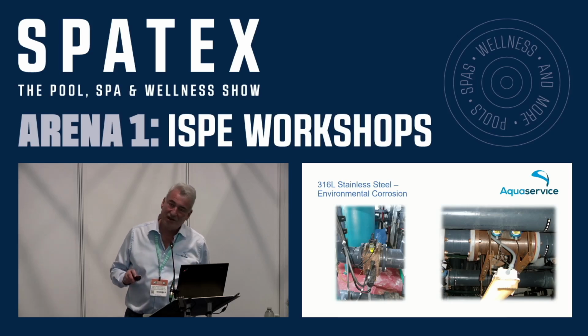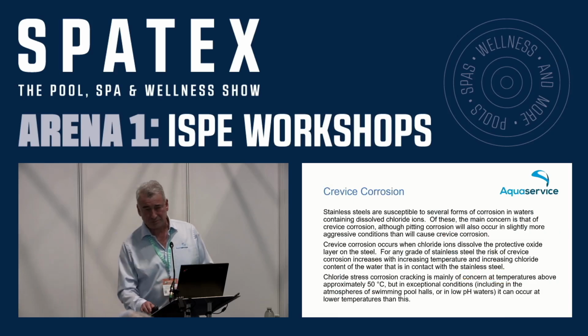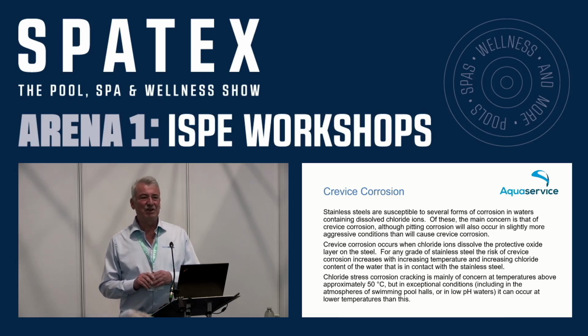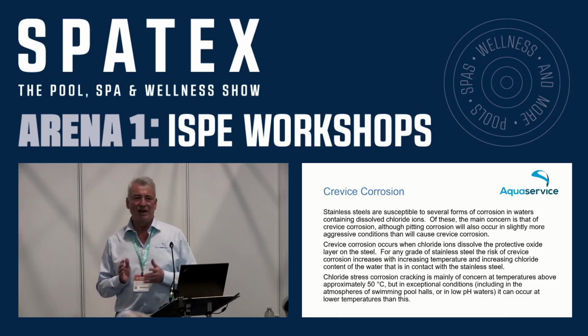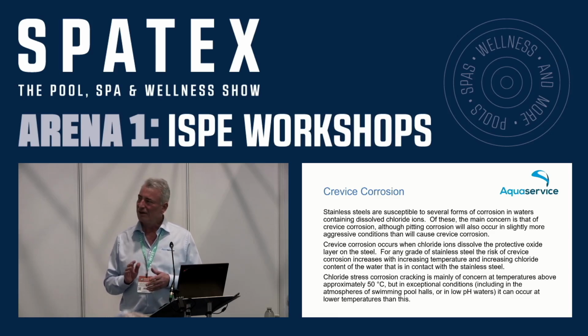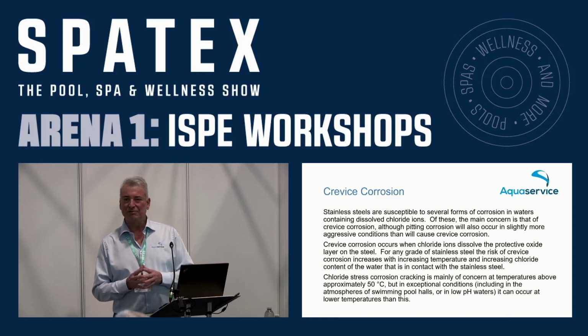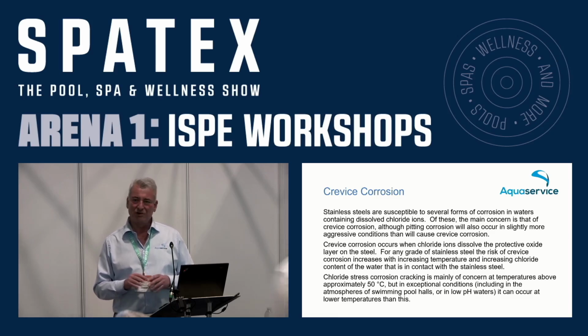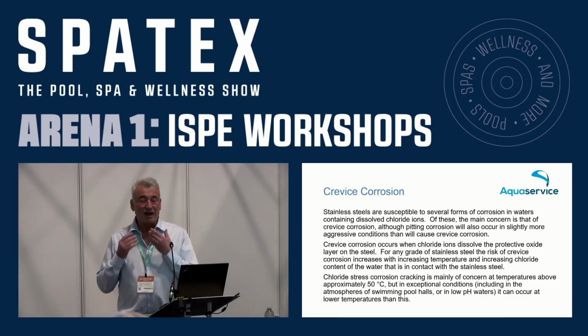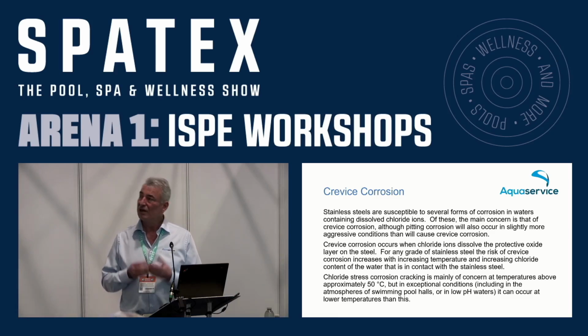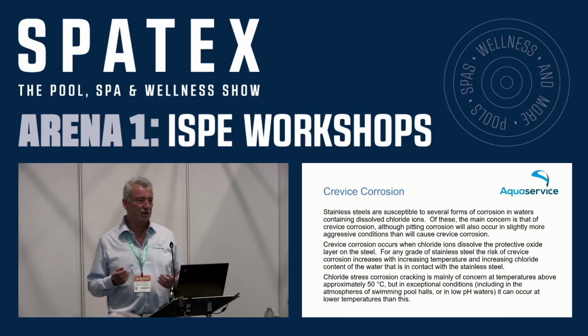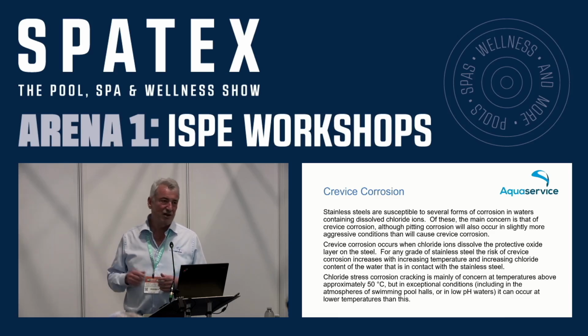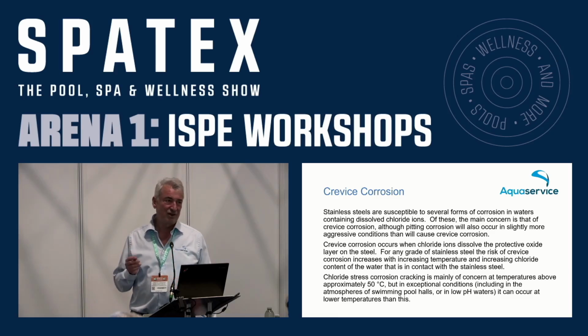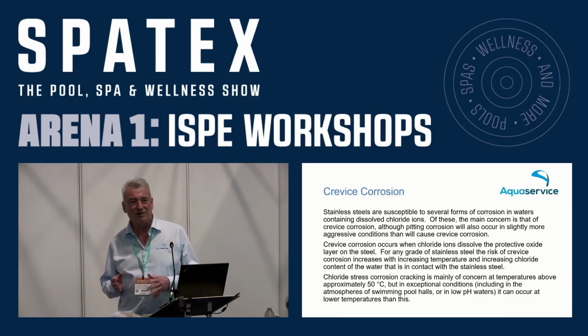What is somewhat more serious is a form of corrosion called crevice corrosion. Now this occurs in what is defined as a crevice, in this case a very small space between adjoining material components, as small as between 0.1 microns and 1 micron. Now stainless steel protects itself from being corroded by a layer of oxide that forms on the surface of the steel. That oxide layer in a pool will be attacked by chloride ions, but the steel replaces the oxide with oxygen drawn from the surrounding water. But in these small crevices, the water's starved of oxygen. So somewhat surprisingly, this type of corrosion is actually indirectly linked to an absence of oxygen rather than its presence.